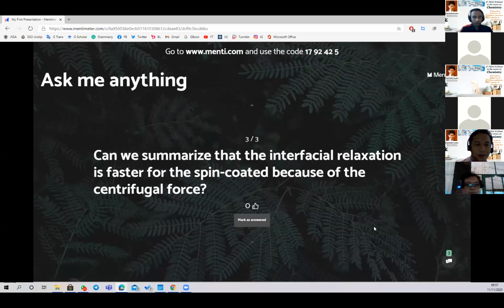Yeah, the last one. I think this is the last question. Can we summarize that the interfacial relaxation is faster for the spin-coated film because of the centrifugal force? Interfacial relaxation is very much slower than that in the internal region. However, if we compare interfacial relaxation between films prepared by two different techniques, spin coating and solution casting, in that case, the answer is yes. The film made by spin coating has a faster interfacial relaxation. Yes.